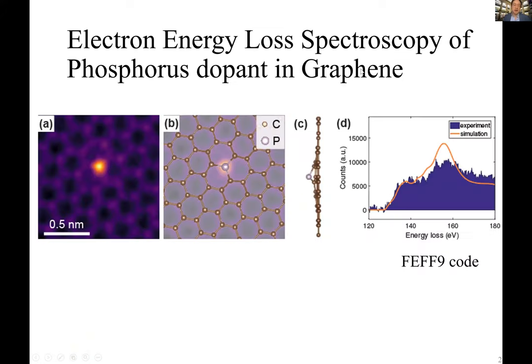So I'll start by showing something that we can get in a transmission electron microscope. We're looking at the electron energy loss spectroscopy of a 2D material, graphene, but with a phosphorus atom here as a dopant. What we do is scan a 200 or 300 kiloelectron volt electron beam across the 2D material and look at how much electron energy loss is occurring at a given spot. There is an ab initio code called FEFF9. When we compare the computed electron energy loss with the measured one, we always see quite a big difference. When we do the calculation, initially we assume this phosphorus atom is stationary.